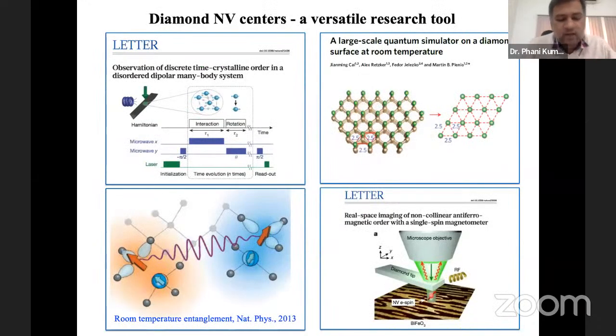Before I delve deep into the research that we have been doing, I want to emphasize that these diamond NV centers have emerged as a versatile research tool in several areas of physics. By incorporating a single NV center into the tip of a diamond cantilever, this can act like a scanning probe. This scanning NV center can be used to measure magnetic fields with very high spatial resolution and also single electron spin sensitivity. It can measure magnetic fields from even a single electron spin under the appropriate conditions.